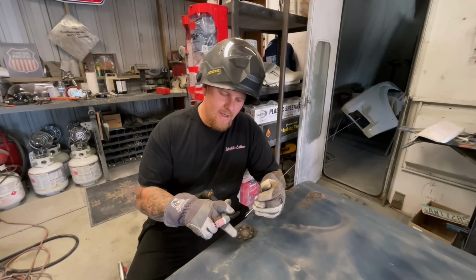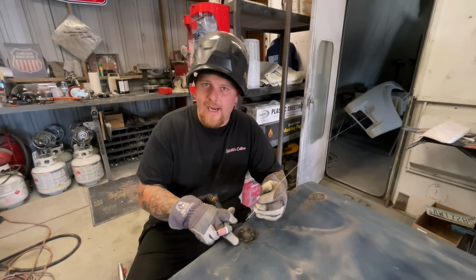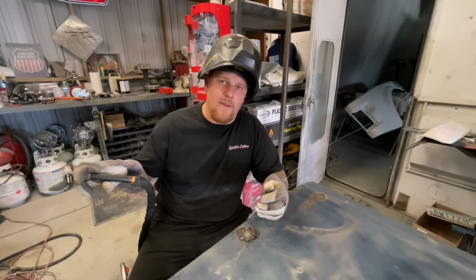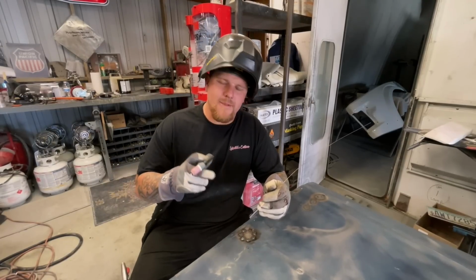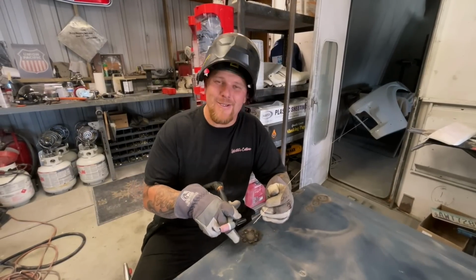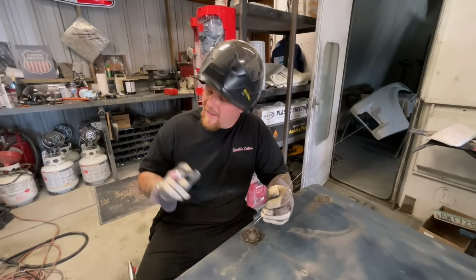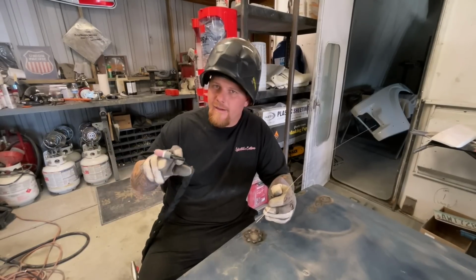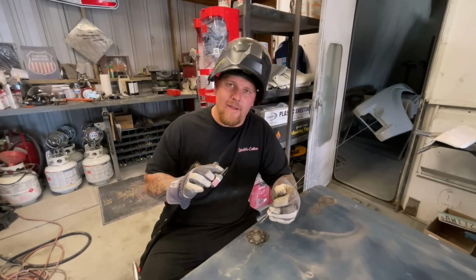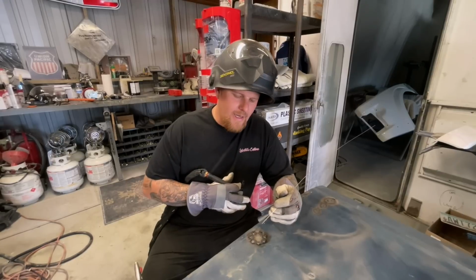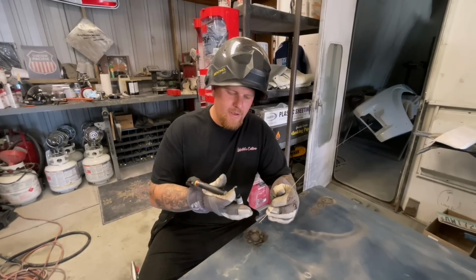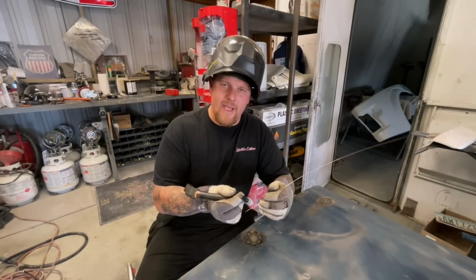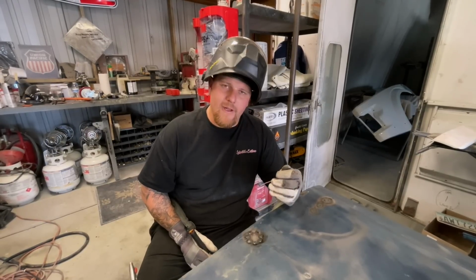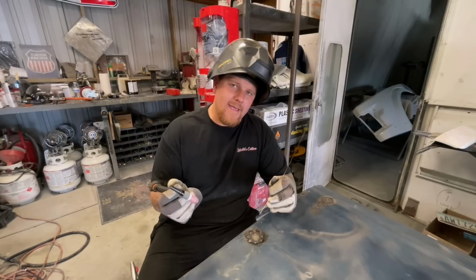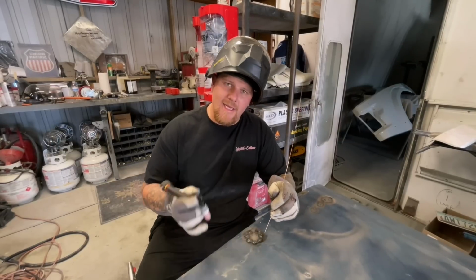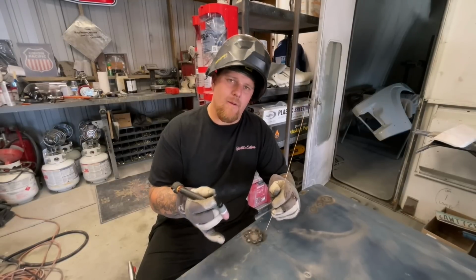So this is approximately 43 amps. You should be somewhere in the ballpark of 43 for 43 thousandths of an inch thickness sheet metal. I usually set it a little bit higher than the 43 on the TIG welder, and that way you can melt the two together. Because if you had a thicker filler rod, it would take more heat to melt it into the two, and then you have more warpage.